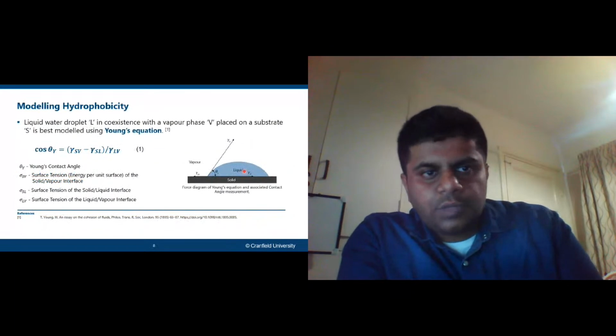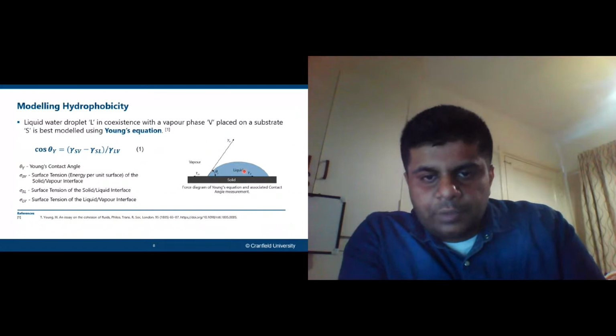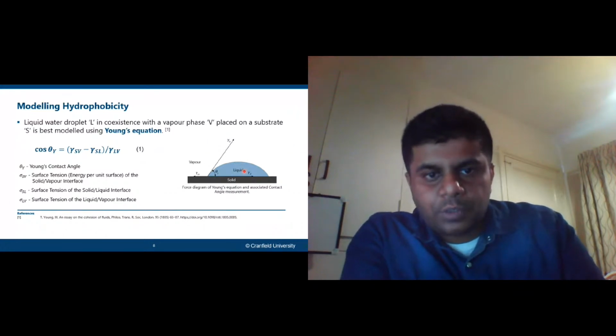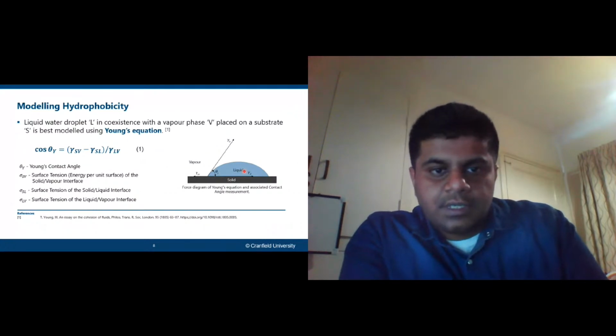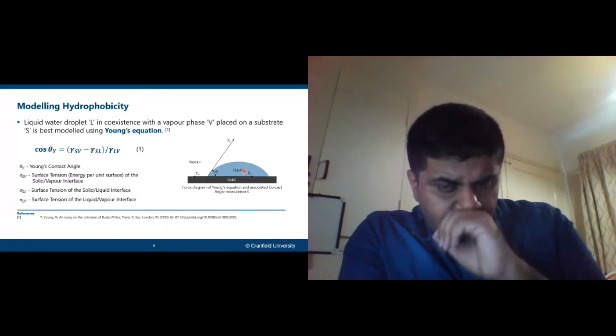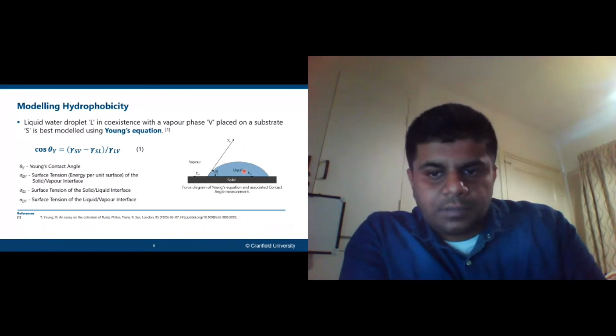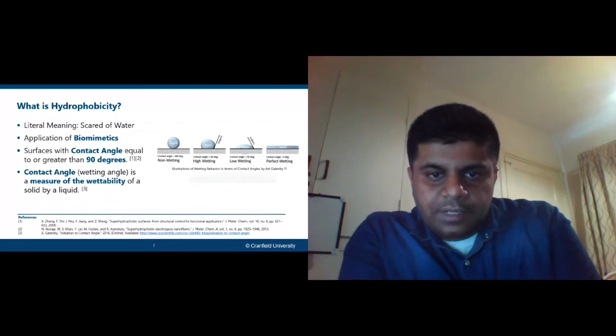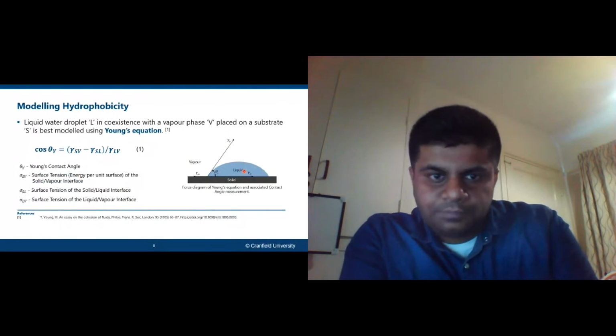So moving on, you can model hydrophobicity by Young's contact equation. It's a well-known equation that was developed in 1805. There are subsequent models developed onto it, known as Wenzel and Cassie-Baxter, which we can discuss in the next few slides. The equation states that the cosine of the water contact angle is the difference of the surface tension between the solid-vapor and solid-liquid interfaces divided by the liquid-vapor interface. So the contact angle calculation on this site is calculated using the Young's contact model.